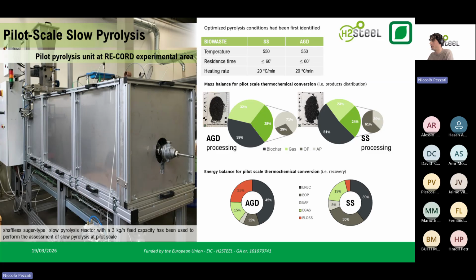So we have 51% solid yield against 29% solid yield, as you can see in the pie charts. And this is due to the higher ash amount in the sewage sludge than in the agricultural digestate, which are not degraded by thermochemical treatment, and so concentrate in the solid product, giving a higher solid yield.